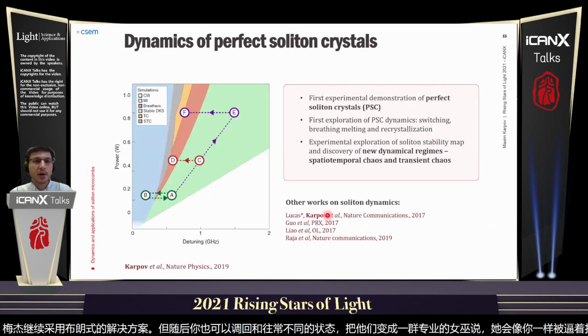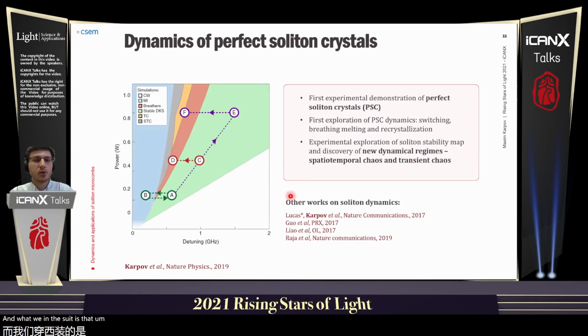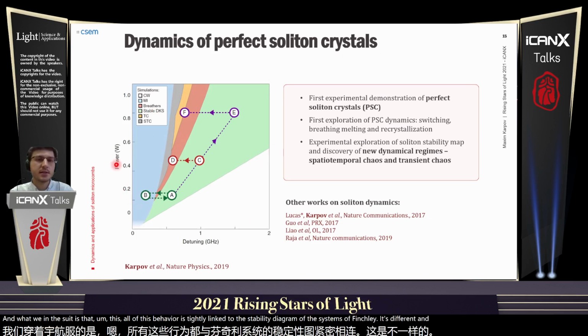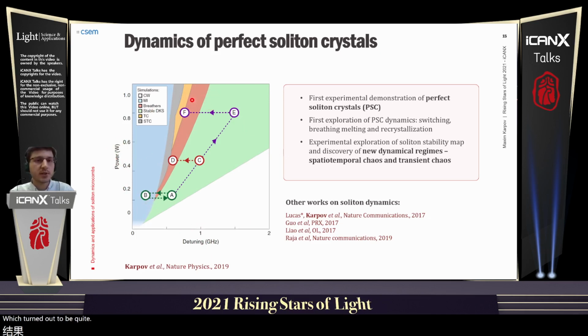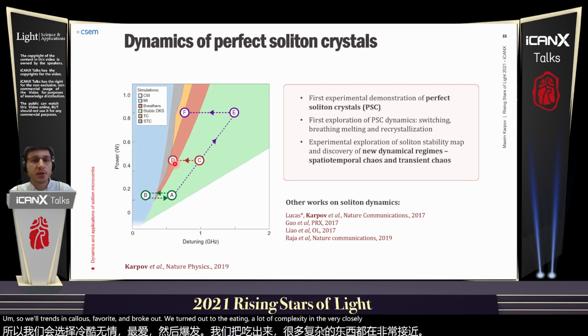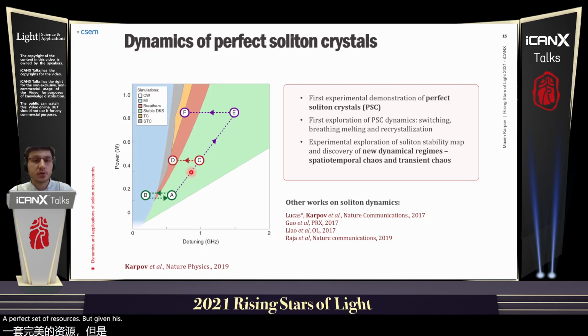What we understood is that all of this behavior is tightly linked to the stability diagram of the system. So essentially, it's different states in the map of detuning and power of the system, which turned out to be quite complex. We experimentally discovered several new regions, so-called transient chaos and spatiotemporal chaos, which add a lot of complexity to the dynamics, not only of perfect soliton crystal states, but even of regular soliton states.